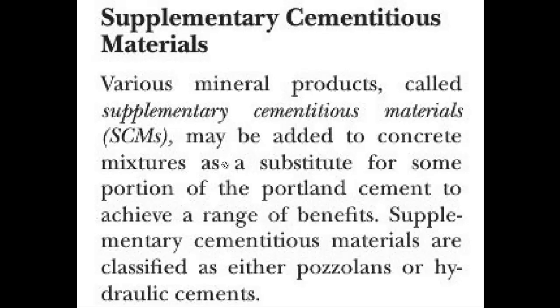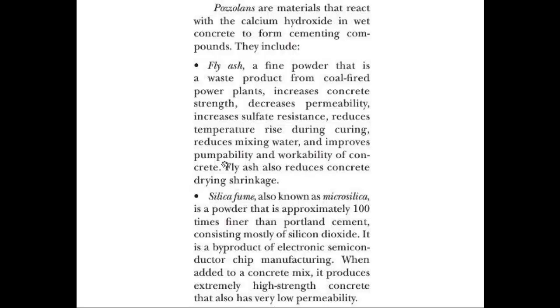Supplementary cementitious materials include pozzolanic materials that react with calcium hydroxide in wet concrete to form cementing compounds. Fly ash — a powder waste product from coal-fired power plants — increases concrete strength, decreases permeability, increases sulfate resistance, reduces mixing water, improves workability and pumpability, and reduces shrinkage. Silica fume, also known as micro silica, is about 100 times finer than Portland cement and is a byproduct of semiconductor chip manufacturing; it produces extremely high-strength, low-permeability concrete.